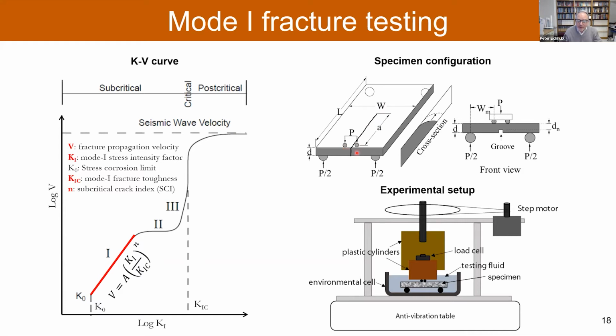And the neat thing about this is that we can submerge the wafer into a bath of water. So we can change the environment in which the fracture propagates. We can change the pH of the water, we can heat it, we can bubble CO2 into it and change the pH. We can add HCl and make it even more acidic, or we can make it more basic. The one thing we can't do is change the pressure, because it's open to the atmosphere.